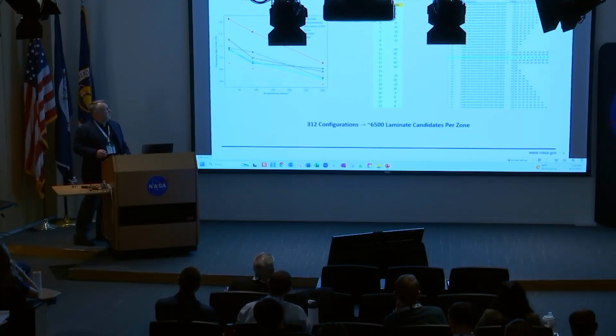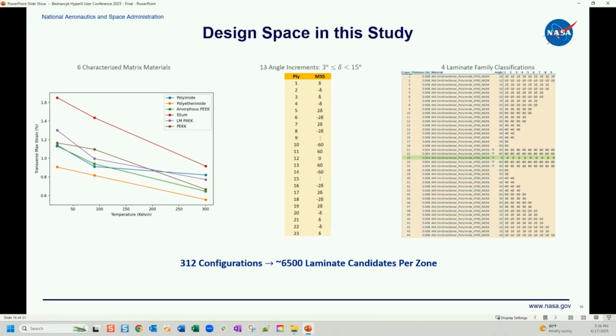So the design space in this study that we did, it's not that big. It's 312 laminate family configurations, based on those 4 different rules and the bounds we set on them. Essentially, the Python is going in and applying that rule and generating a laminate family each time it's doing iterations. Here are some examples of 4 laminate family configurations. You can see all of them have this thin ply pack in the middle. And then we have 6 different ply materials that were generated based on the 6 different thermoplastic materials. Okay.